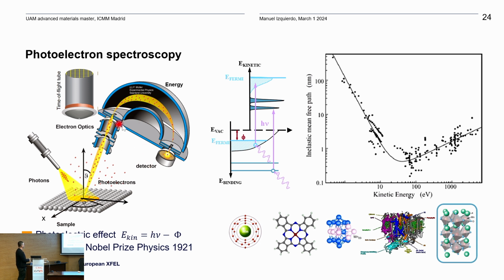There are two basic types of spectrometers, hemispherical or time of flight. And for time resolved, for the moment, we are using the second one. You can study all systems that you want. You have seen some examples of atoms at SQS, but you can also study molecules on substrates, solids, bio-objects. Something that is important is that the photoelectrons have this universal curve. If the kinetic energy of your electrons is in the order of 45 electron volts, you will sample the last layers of the surface. If you increase to 3 keV, then you are able to sample depths in the order of a few nanometers.